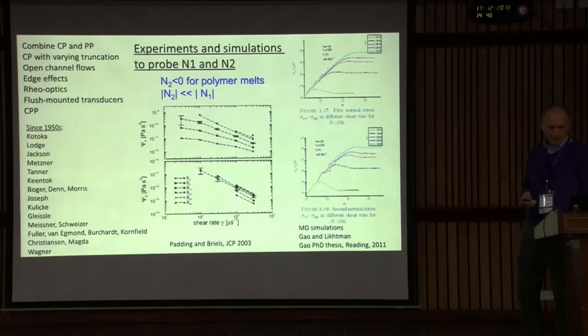What's the problem with measurements? The main problem is edge fracture. You measure with a cone on a plate, and eventually your sample may be expelled, yet the rheometer still provides data — this is not good. Even worse, sometimes the effect is weaker: there are some stripes indicating a fracture already taking place at the edge. The sample can also be a little misplaced — fracture and slip, etc. One has to account for this.